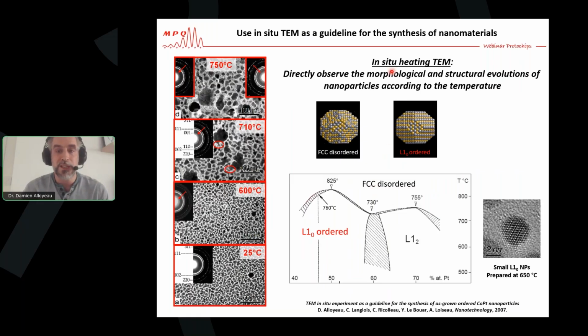So we wanted to better understand why we had this out-of-equilibrium structure. We decided to do an in-situ heating experiment to directly observe the morphological and structural evolution of the nanoparticles as a function of the temperature. And this experiment is shown here. When you increase the temperature, you see that at 600 degrees, it takes about 10 minutes to see the appearance of the chemical order. At 700 degrees, you see that you have a lot of growth mechanisms and a drastic size increase of the nanoparticles. Your particles are well ordered. You see the superstructure reflections. And then at 750 degrees, you see the phase transition that is seen here on the bulk phase diagram.